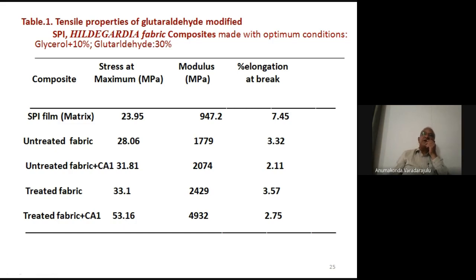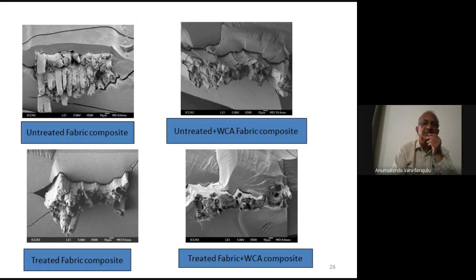The polyethylene will be having a strength of 25 to 35 megapascals. So our film has exceeded that of the polyethylene itself, because we used a uniaxial fabric as the reinforcement and so on. Modulus increased from 947 to around 5,000 and so on. So these are superior properties when compared to the commercial polyethylene or polypropylene films. And then we studied its fractographs.